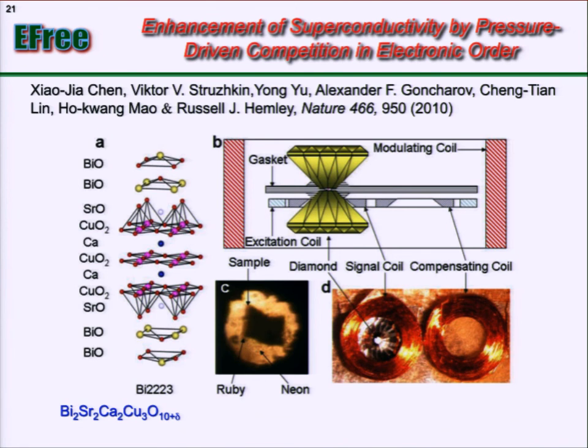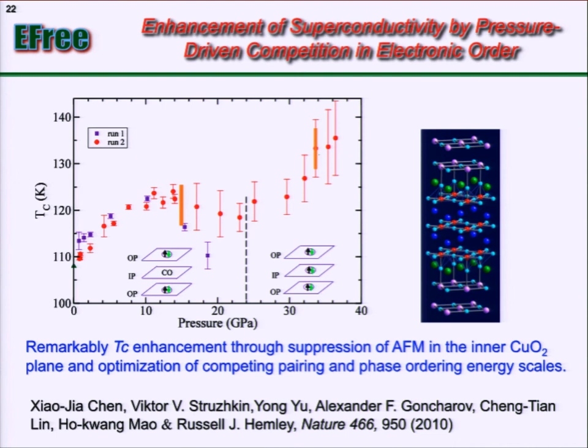But if you do it chemically, you can only put oxygen in or take oxygen out. If you do high pressure, you can compress different layers of oxygen differently, because under pressure they respond differently. Pressure can have a similar effect: you optimize and overdope one layer, while the second layer is still underdoped, so you can have a second maximum that can push the superconductivity much higher. So this would be a way to design an oxide superconductor to make it higher.